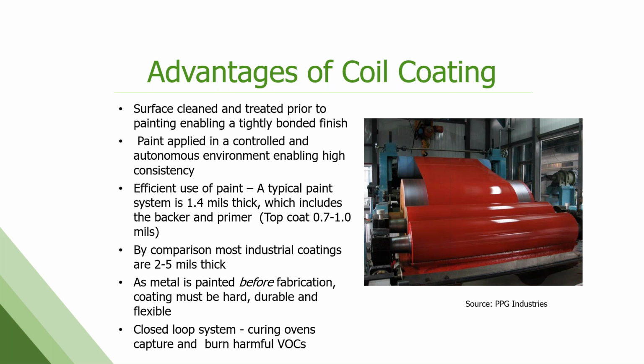Typical paint system is about 1.4 mils thick. I'll do the math for you. That's 0.0014 inches. For comparison, paper is 2 to 3 times thicker than that. I'm going to layer a paint on that's thinner than paper. By comparison, most other industrial coatings, including automotive, are 2 to 5 mils in thickness, so a substantial difference in